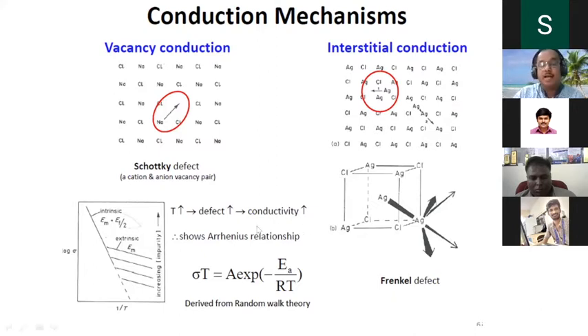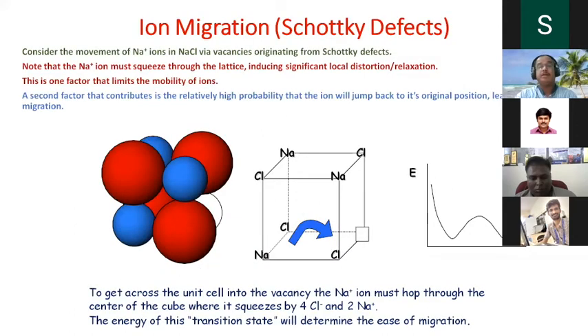That's what I call the Arrhenius relation, sigma equals A exponential minus Ea by RT, where Ea is the activation energy. So energy required for the jump from the occupied to the unoccupied site. If the energy is less, then very fast lithium ion conduction. If you require a very large amount of energy to jump, I think conductivity will come down. This is based on random walk theory. I'm just giving the basics.